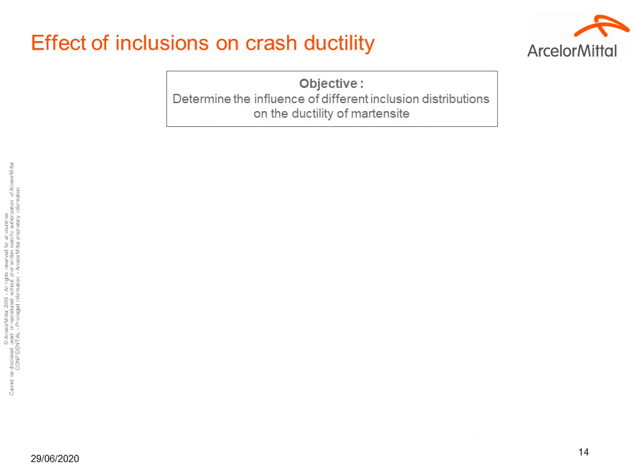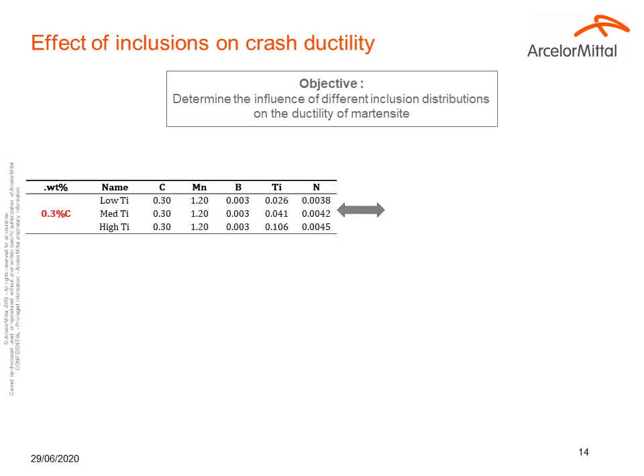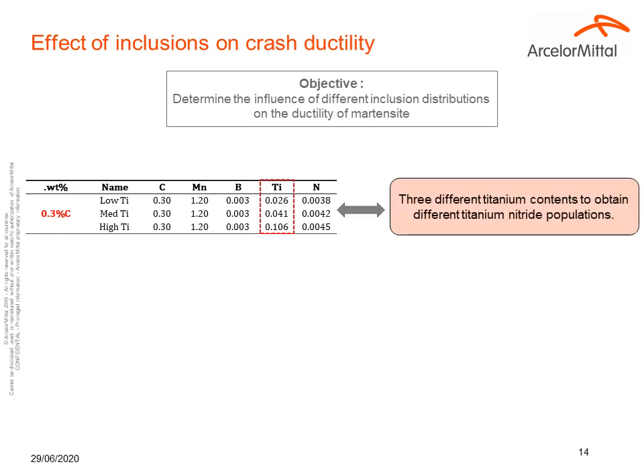The second study of this presentation is about the effect of inclusion on crash ductility. The objective is to determine the influence of different inclusion distribution on the ductility of martensite. To do so, we use 0.3% carbon martensite steels with 3 different titanium contents in order to obtain 3 different titanium nitride populations and study their effect.